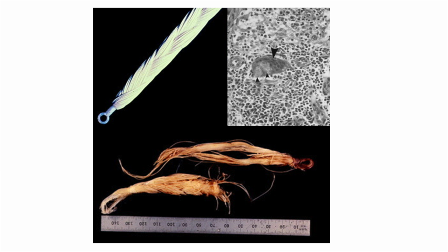What characterized those polyethylene and polypropylene implants was that they had a woven or braided structure. The transverse nature of the fibers in that woven structure in the intra-articular portion was thought to be a problem because it didn't stand up to torsional or shear stresses. So they broke down, they generated wear particles, and as shown in the histological slide on the right, those wear particles then started popping up in lymph nodes distal to the knee.